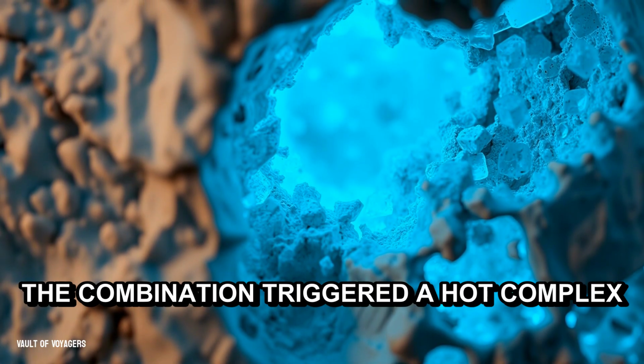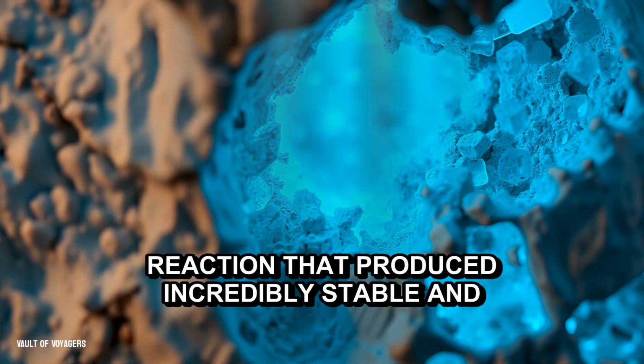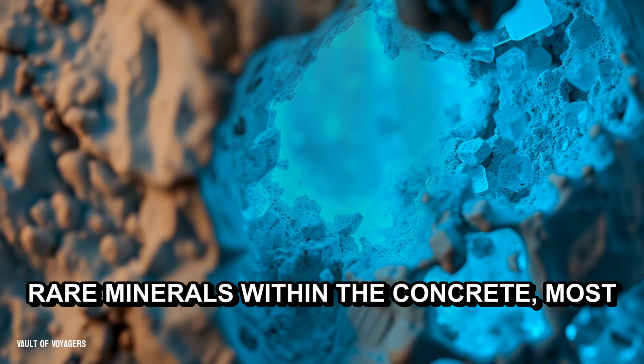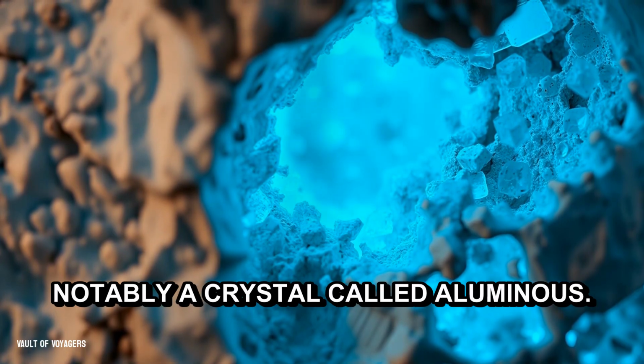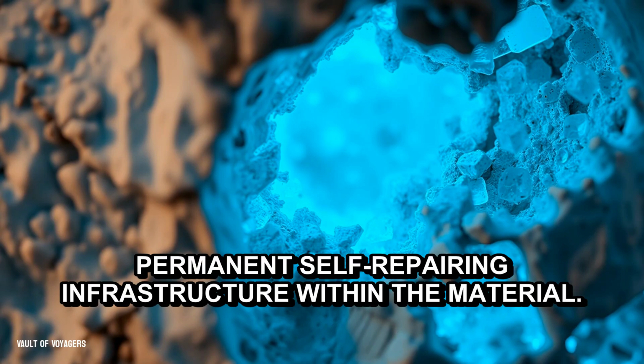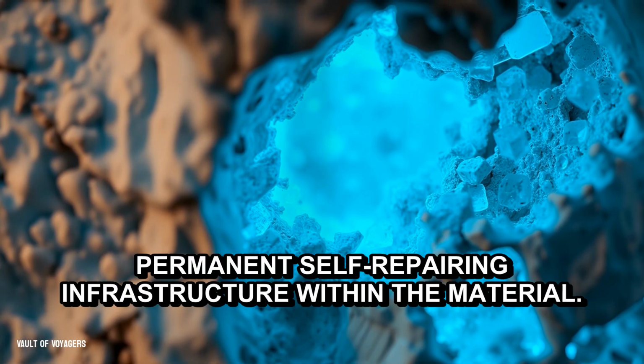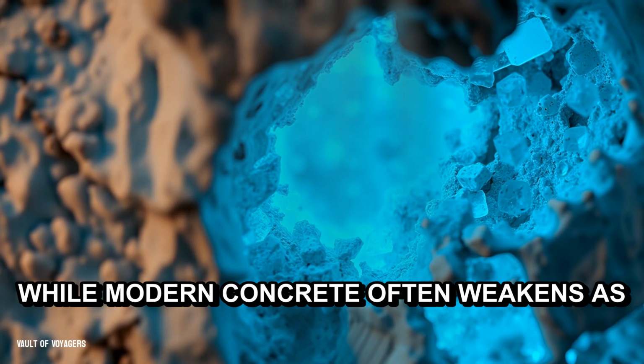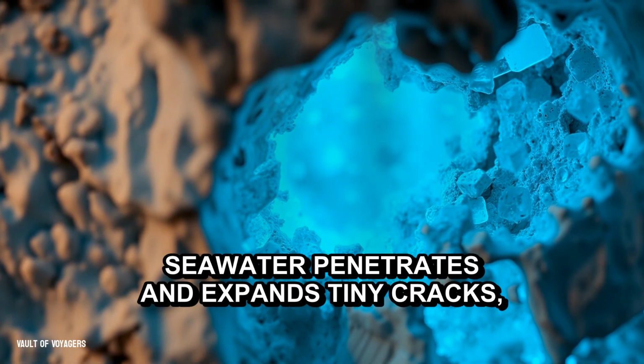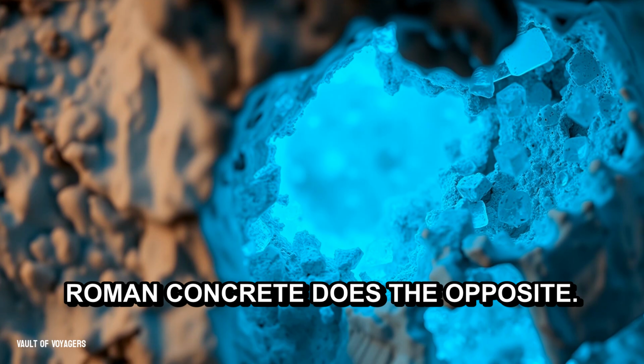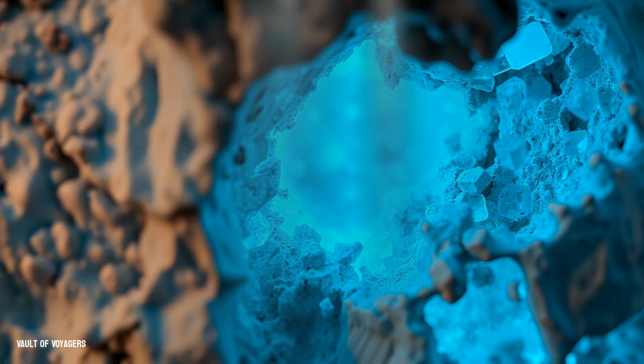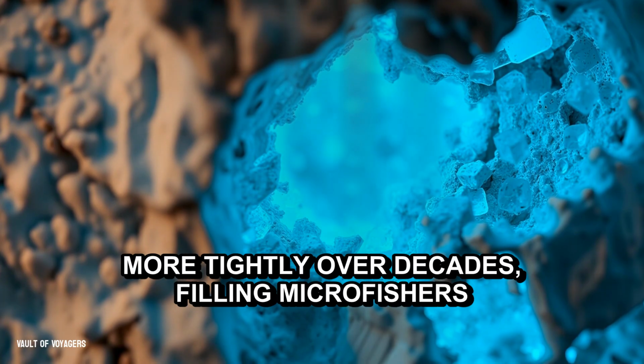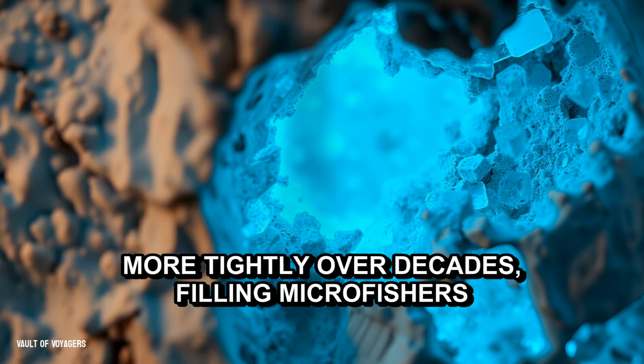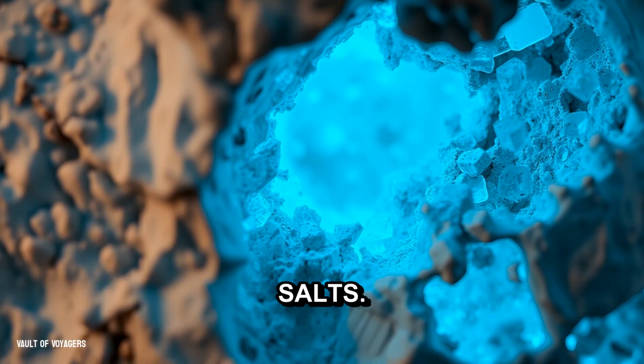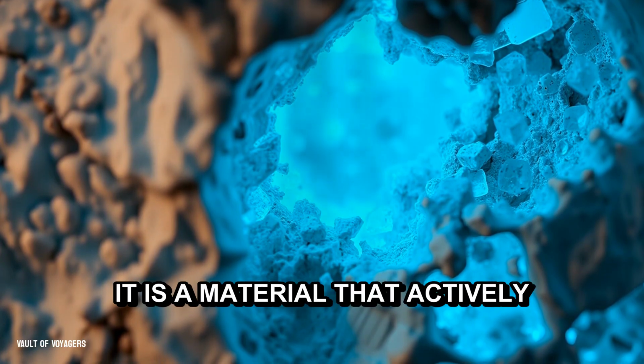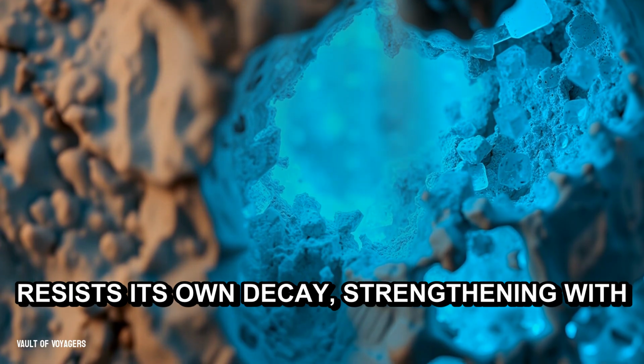The combination triggered a hot, complex reaction that produced incredibly stable and rare minerals within the concrete, most notably a crystal called aluminous tobermorite. Think of these crystals as a permanent, self-repairing infrastructure within the material. While modern concrete often weakens as seawater penetrates and expands tiny cracks, Roman concrete does the opposite. The crystals actually grow and interlock more tightly over decades, filling microfissures and blocking the path of corrosive salts. It is a material that actively resists its own decay, strengthening with age.